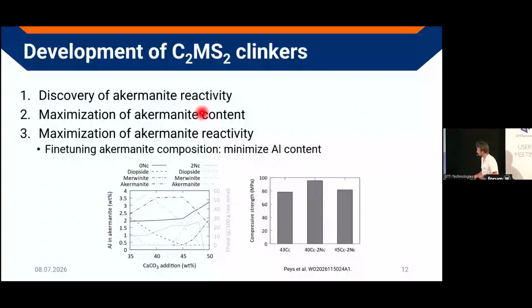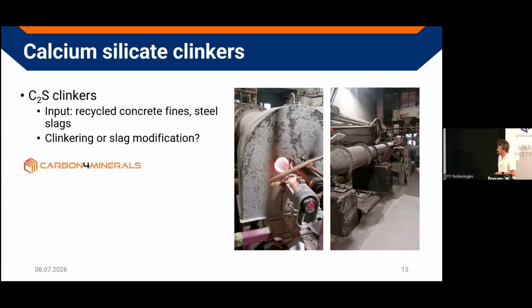Yeah, and then we could increase the strength even a little bit further towards the 100 megapascal. On small paste compacts, to be clear, and so that it's the region where, if you would make a paste compact of an OPC, it's quite similar to that, I think. Okay, that was the main part of my presentation, the new calcium magnesium silicate clinkers.